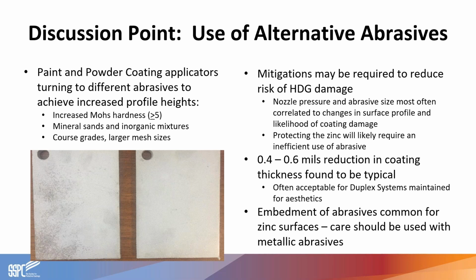And because the longevity of the hot dip galvanizing is directly related to the amount of zinc present on the part, this may appear as an undesired quality. And so you may want to evaluate that on a project by project basis to determine if that's an acceptable trade-off in terms of overall longevity. For projects where you're going to be maintaining the duplex coating, the painting or powder coating over, this is going to be much less of a concern. This is more of a concern for projects where you're not looking to maintain the duplex system. You're just looking for a one-time, greater longevity product.